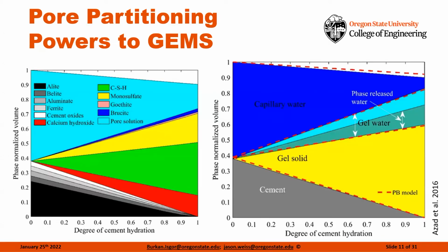So what we're able to do here is apply a model called the pore partitioning model. We're going to take the outputs of the thermodynamic model, where we have the initial cement phases or SCM phases going into the system. We have our initial water, and we're able to compute the reacted products. Now, once we do that, we can start to characterize these into the phases that would be more similar to what someone like Powers used to describe the overall system. So Powers described that you have the cement phase and the water phase. They come together to produce the gel solids and the gel water.